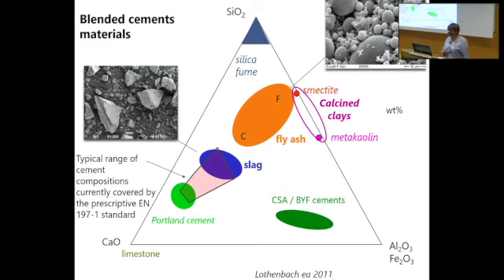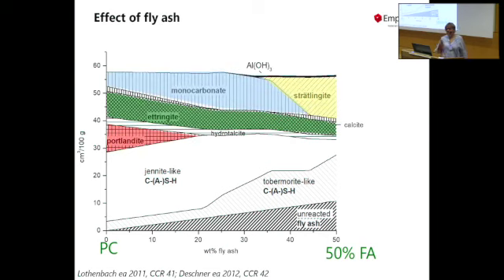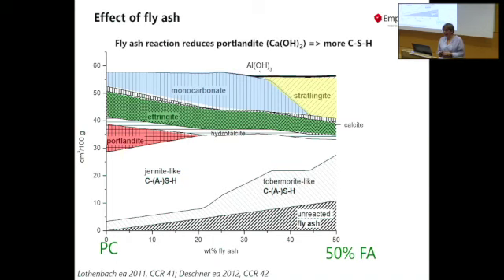And naturally we also can use thermodynamic modeling to figure out what's happening. This is an example from Portland cement mixed with fly ash, and the Portland cement itself contains some limestone. So basically what you do if you mix fly ash in the system, you start to consume the Portlandite, because the fly ash is rich in silicon and aluminium, and you start to make more and more AFM phases, monocarbonate, and eventually strätlingite. The third thing you do is also you lower the calcium to silica ratio of your CSH.